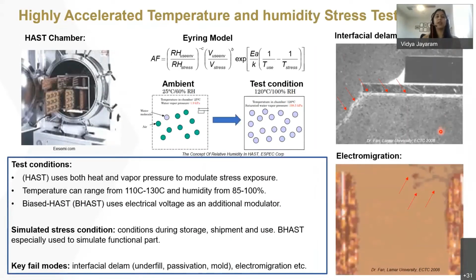Another really effective stress test is the humidity accelerated stress test. The unique thing about this is, in addition to the temperature component, you also add a humidity component to the testing. The concept is to completely saturate the chamber with moisture and keep it at a high temperature. A variety of HAST tests are available, where you have unbiased versus biased HAST, where a biased HAST would also include passing an electrical current through it, which is an additional modulator that would maybe simulate what your package is experiencing in a more realistic scenario.